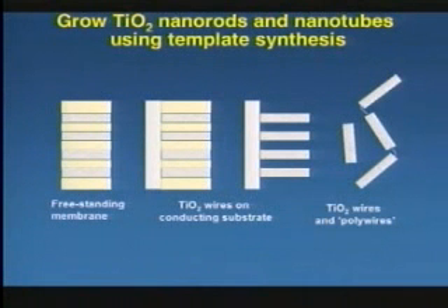If you fill them under controlled conditions in a sol-gel process, you only coat the sidewalls of those pores. Then you can either release those and make soda straws that are basically current collectors, or you can fill them up with something else as the photoactive rod. Their thickness is defined by the thickness of the aluminum that went into making the alumina, so they can be millimeters thick or hundreds of microns thick. And so we make hundreds-of-microns-long rods that are a few nanometers in diameter.